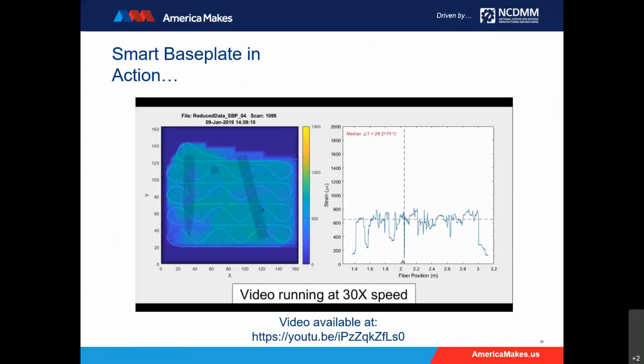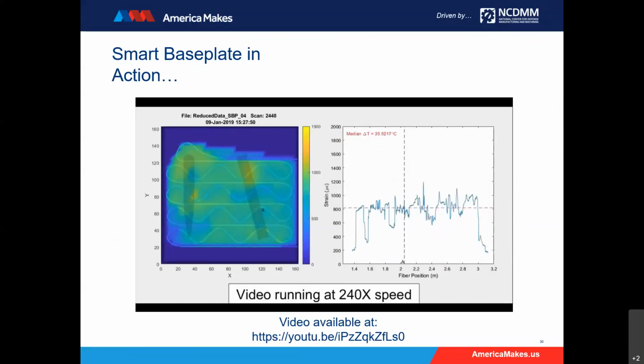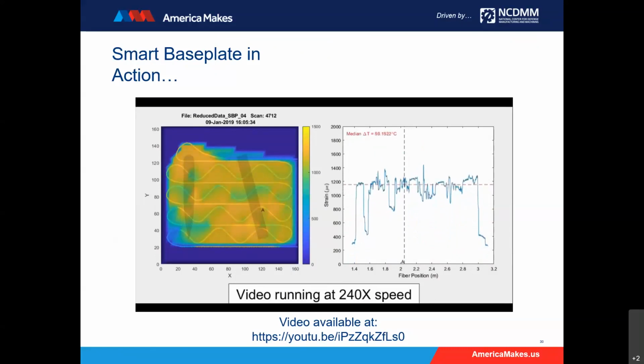And then we had several features here that obviously are not designed for a good powder bed outcome. Some of the sharp shapes were there on purpose so we could see if we could detect delamination, a separation, a part peeling up. And what we found out is we could actually see a delamination or a build plate failure quite early and track that as it delaminated. And we never hit the recoater blade. So we were able to continue to see our defect and how it evolved before we ever would have seen it from the outside. So it's just an interesting tool. And again, it's all about how can we leverage these additive processes to help one another. And this is just another cool application.